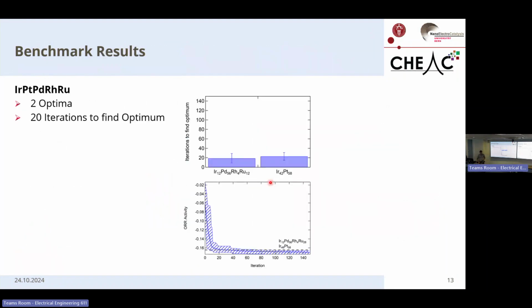So moving on to the results, the first space is the iridium, platinum, palladium, rhodium, ruthenium space, which has two local optima, with similar activities. And on average, it takes 20 iterations to find both of these optima. So if you need just 20 experiments to find the optimal compositions among 4 million possibilities, that's relatively fast. It's also a number we can do in the lab.